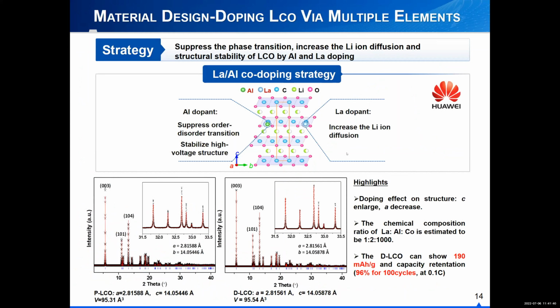This is a collaborative work with a Huawei company. Here we try to choose two dopants to suppress the phase transition and increase lithium ion diffusion and the structural stability of lithium cobalt oxide. One is aluminum and one is lanthanum. The aluminum right here, we try to suppress the order-disorder transition and stabilize the high voltage structure. And the lanthanum right here, we try to increase the lithium ion diffusion. And finally, we found that the obtained product can show about 190 milliampere hour per gram, and the capacity retention could be as high as 96% for 100 cycles. So this is a very good material.